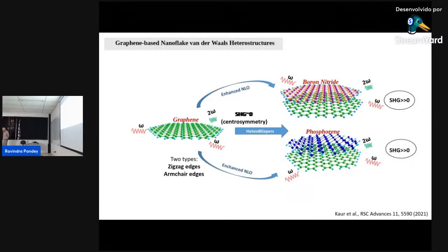This is a very interesting material coming out. We have electronic properties, mechanical properties. What about the optical properties? Because as you know, there's a push for optoelectronic devices. Most devices are silicon. Silicon is an indirect gap material. You cannot use silicon for optical devices. So what you do, you have a chip, an electrical device and an optical device. So they want to merge in the same place, optoelectronics. So graphene is a centrosymmetric material. So what we have is the so-called second harmonic generation, which is a non-linear optical property. It cannot have it. It's like a zero gap material. It's happy as it is now. So the idea is how to perturb it. And we want to use graphene because of in-plane high electron mobility.